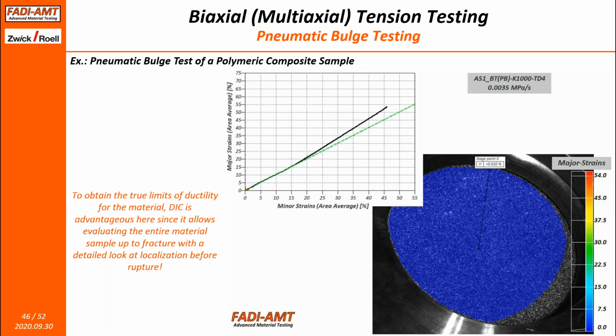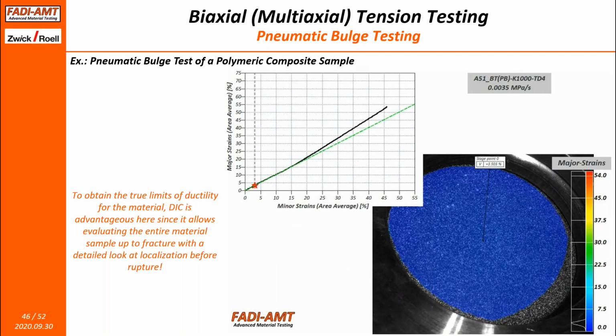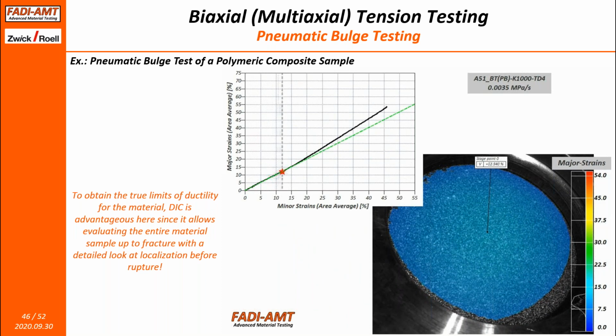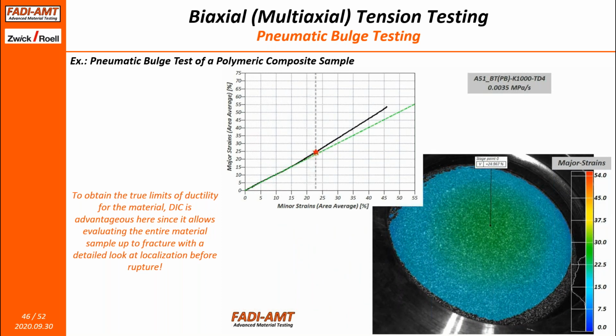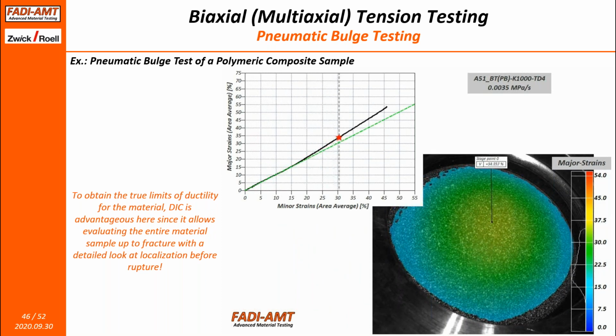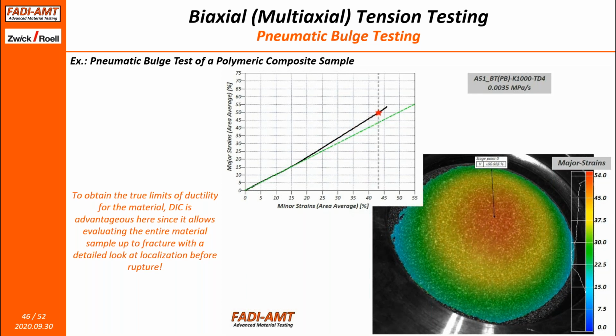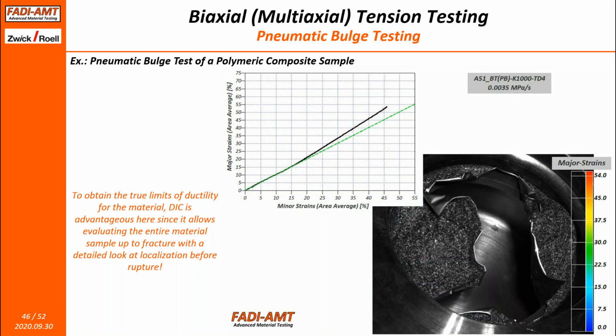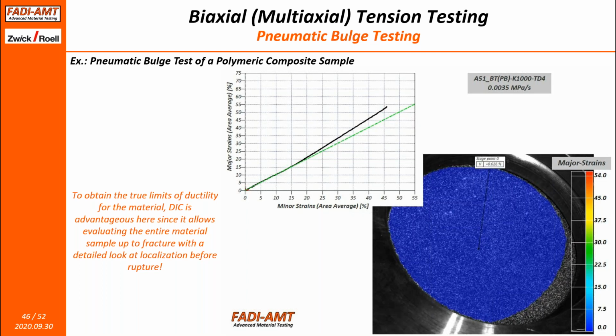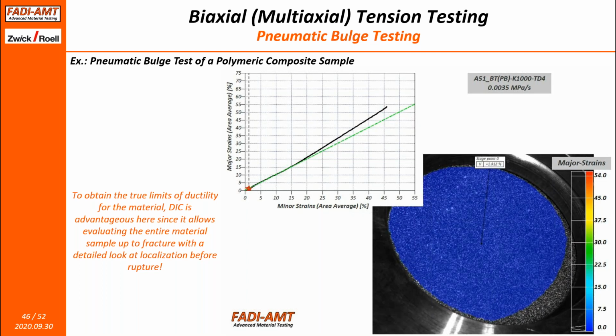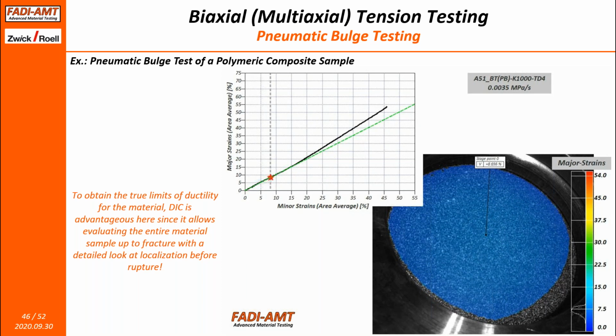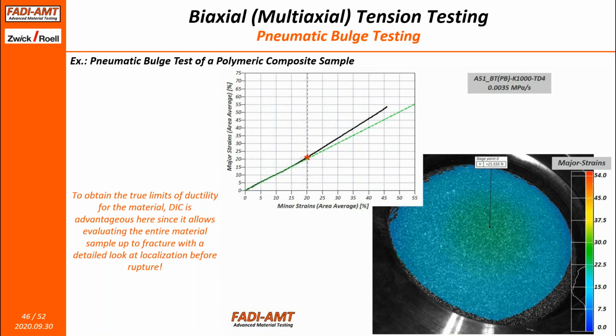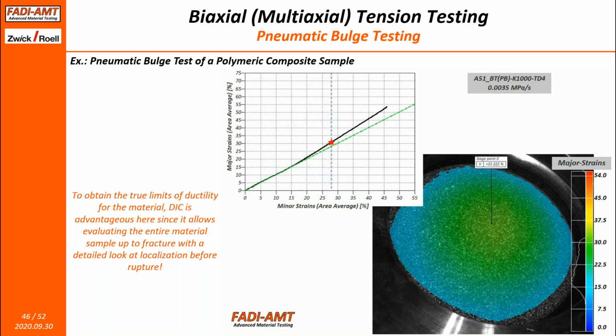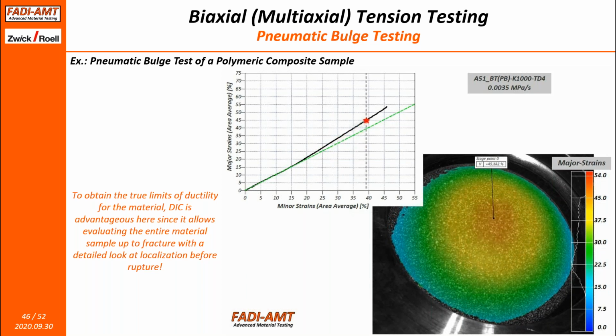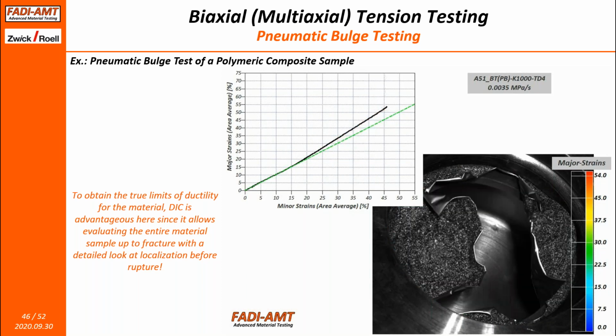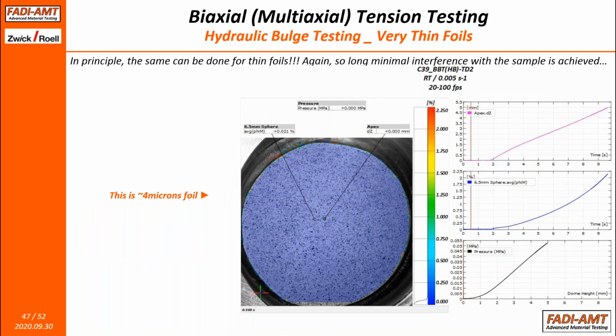Similar test in principle. This is just for a polymeric material, shown here in a pneumatic mode instead of a hydraulic, or instead of liquid, we're just using gas. And as I said earlier, it's technically the same exact principle in terms of the testing approach. We just basically use gas to deform the material. And again, in terms of principle, you can use video or laser extensometry, but if you want to calculate stresses and strains, then you must use DIC in order to capture the curvature of the sample.